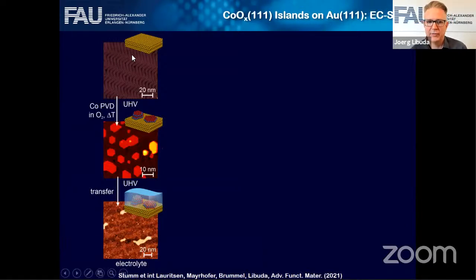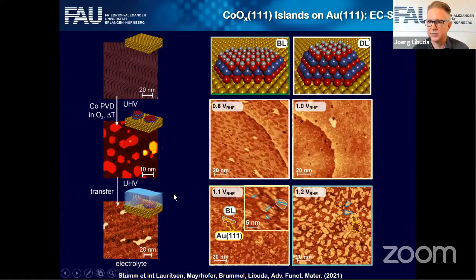So this is an example of cobalt oxide islands that we looked at together with the group of Jeppe Lauritsen in Aarhus. They have made a recipe to prepare these islands on a gold surface. So these are STM images in ultra high vacuum. And then you can bring this system into the electrolyte and do electrochemical STM. It's more fuzzy and the quality is not so good, but it's doable. And then you can look at these structures, and there are different structures. I will show later in the second part. There are these bilayers, double bilayers. You can visualize them under electrochemical conditions.